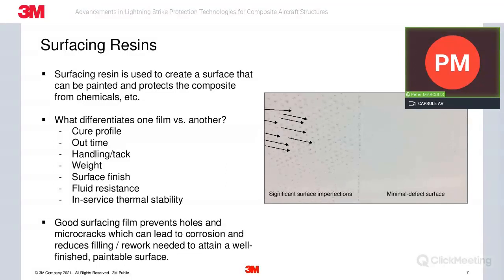In the images on the right here, this is a painted piece of skin. One has a poor surface finish and the other has a good surface finish. In the left image, you could clearly see some pitting. And this is challenging and frustrating because pitting doesn't actually show up until you paint the area or after you have painted the part. So when they are preparing the skin of the aircraft for painting, it's often sanded and prepped, and any defects are filled. And so if your choice of surfacing film can provide a defect-free surface, then you could hopefully reduce a step within the paint preparation process and not be surprised by the possible telegraphing effects of these contaminants through the surface.